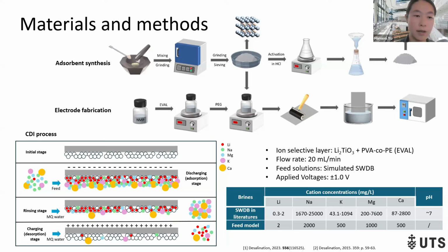And the CDI process is a little bit different from the previous method. After the adsorption process, we introduced a rinsing stage before the desorption stage to rinse out the competing ions, because the lithium can be intercalated into the LTO structure, but other competing ions are mainly only temporarily adsorbed on the surface of the electrode. So the rinsing stage can first remove the competing ions, which improves the lithium selectivity after desorption.